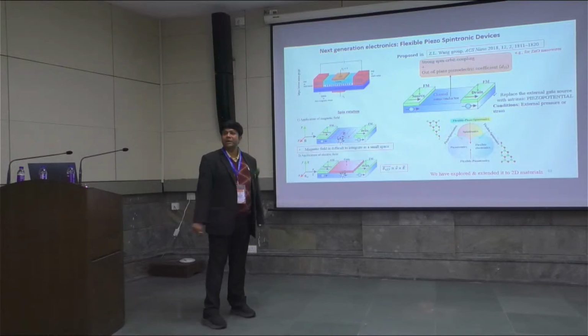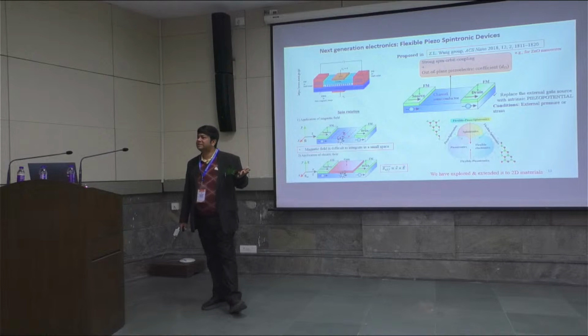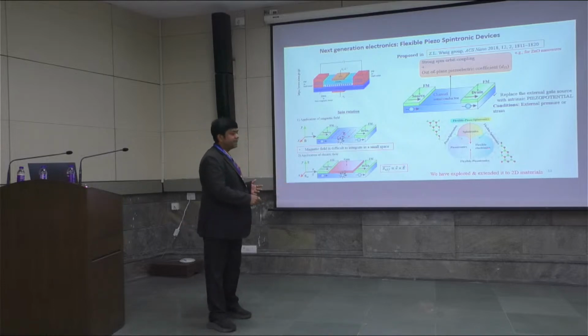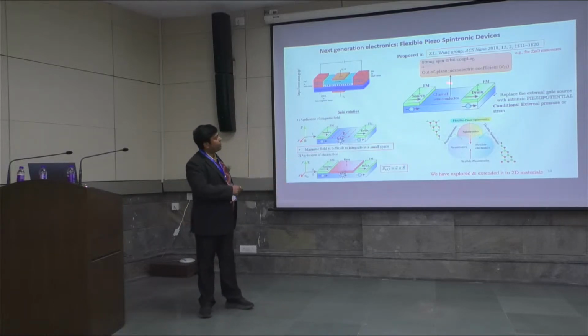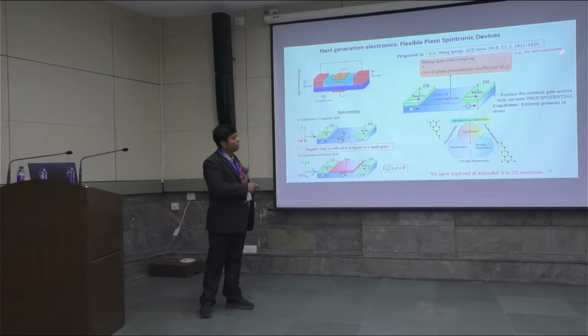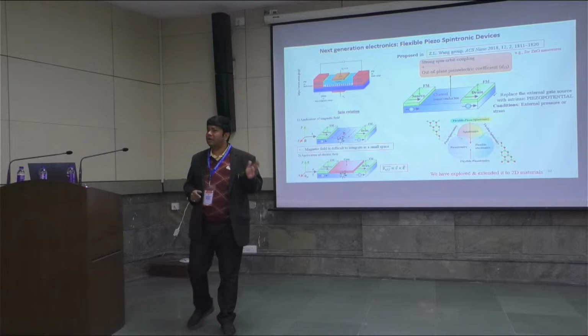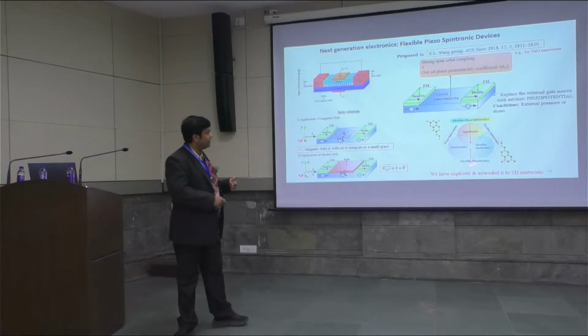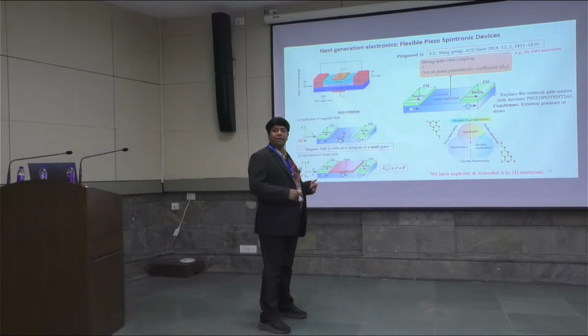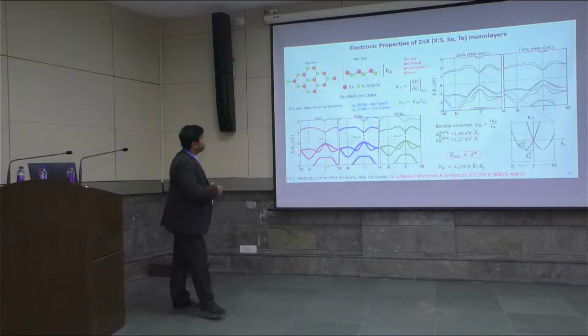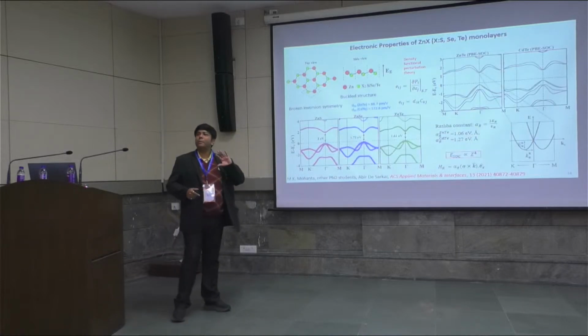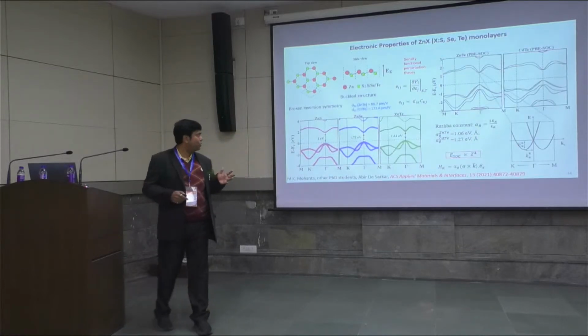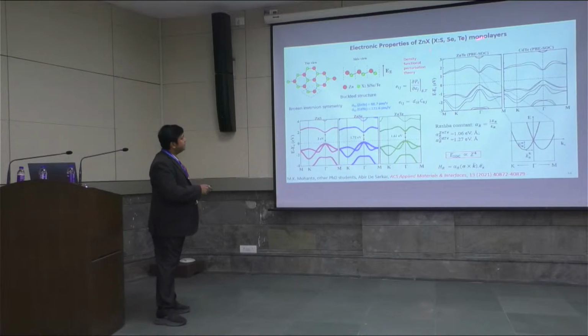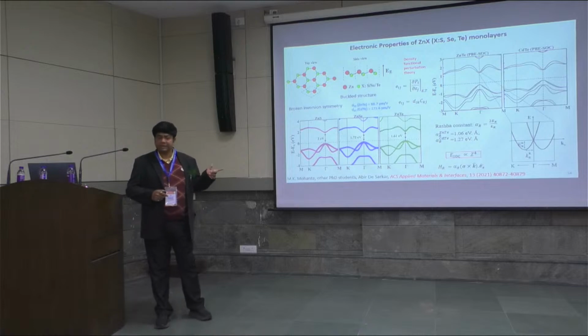And then low dimensional materials by default have a low elastic stiffness constant, and therefore they are flexible and stretchable. Such a pointer was given in this ACS Nano paper by the group of Wang on one-dimensional zinc oxide nanowires, and we have extended this concept to two-dimensional materials. So we have proposed a couple of monolayers which exhibit a combination of all these three properties, like ZnX (X = S, Se, Te) monolayers. They have a polar buckled structure and a hexagonal honeycomb lattice as well.